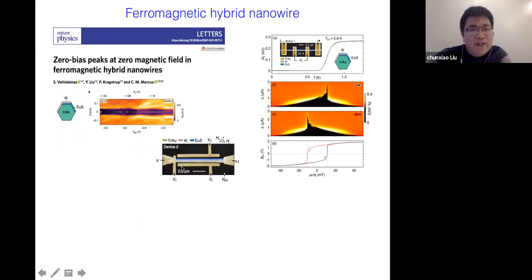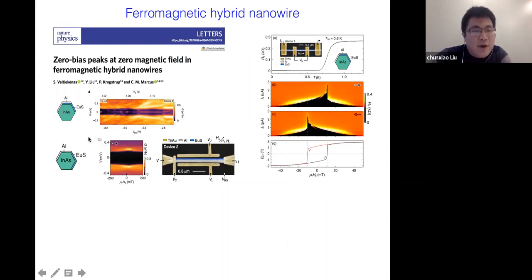Then they measured the tunnel conductance spectroscopy in the NS junction for this hybrid device, and they found a zero bias conductance peak in a finite parameter space for this ferromagnetic hybrid nanowire, which is consistent with the Majorana signature. What's more interesting is that such a zero bias conductance peak is observed only in devices with a particular geometry. In some other devices where aluminum and the europium sulfide do not overlap, such a zero bias peak is not observed, in contrast with this successful device where aluminum and the europium sulfide overlap with each other.